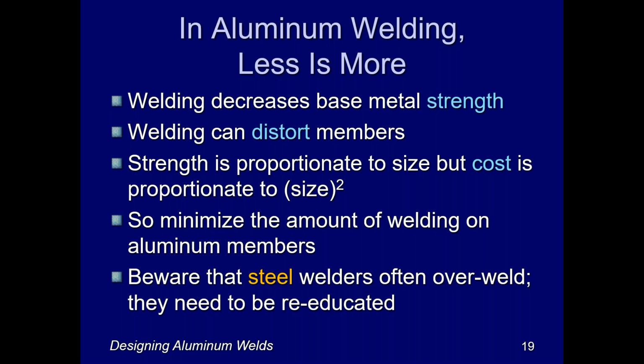Not only that, welding can distort members because you get differential cooling. You have residual stresses that result in distortions, and that can be a real problem. Not only that, the strength is proportionate to the size, but the cost is proportionate to the size squared in any weld, and that applies to steel welds as well as aluminum welds. So as you increase the size, the cost goes up a lot faster than the strength, and that's a problem. So you want to keep your welds small.